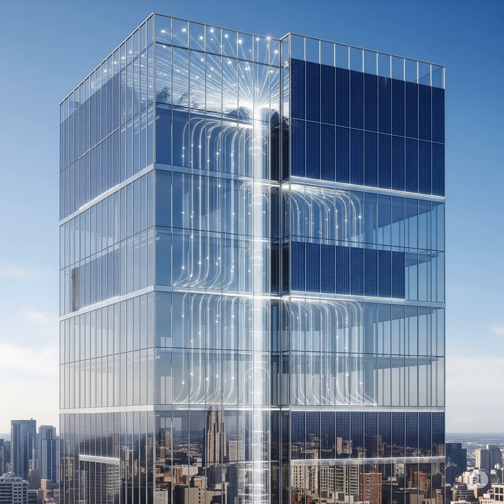Pretty remarkable. Microcells made this way hit a power conversion efficiency, PCE, of 20.1%. 20%. Yeah, which was nearly identical to what they got from unpatterned, basically perfect lab samples. And they showed a stabilized power output of 19.9%. That means it wasn't just a peak, it could sustain that level. And crucially, could they scale it? Make lots of these microcells?